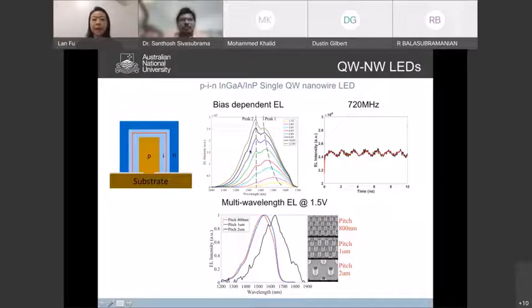And then you can see that from the same substrate, we're able to demonstrate multi-wavelength LEDs with very nice electroluminescence, and we can also modulate them at relatively high speed, 720 megahertz. In fact, recently we did more measurements and we can achieve 1 gigahertz modulation, which shows that they're promising as a light source for optical communication.